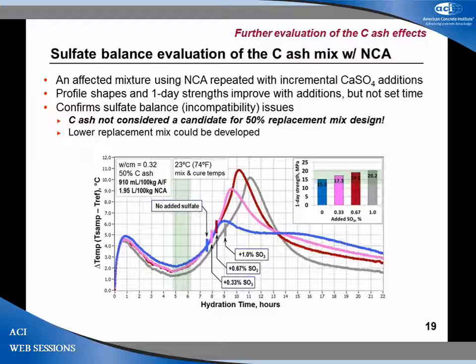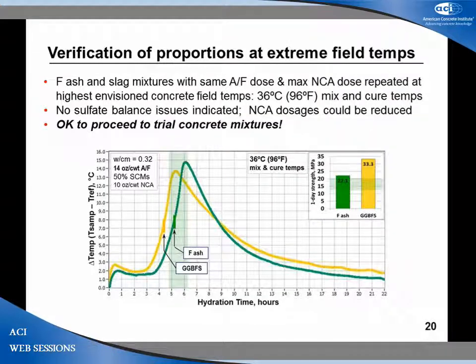So this tells us that for a 50% replacement with this admixture suite at these temperatures, the C ash is not going to be a candidate for us. You might retune that to a 35 or 40% mix or something like that. But then we need to take the mix to our ultimate high concrete field temperatures to see what the performance is going to be in the field on the project. And now we can verify that both in the case of the F ash or the slag mix, you can use either one of those. One-day strengths are ample by the time you do that. We can actually begin to back off on the non-chloride accelerator.